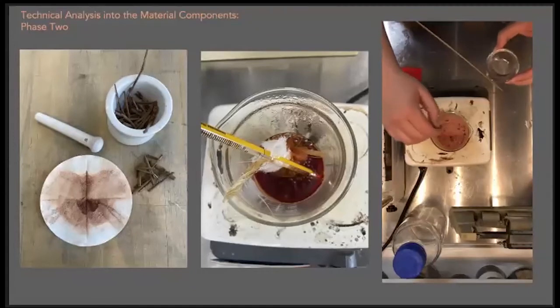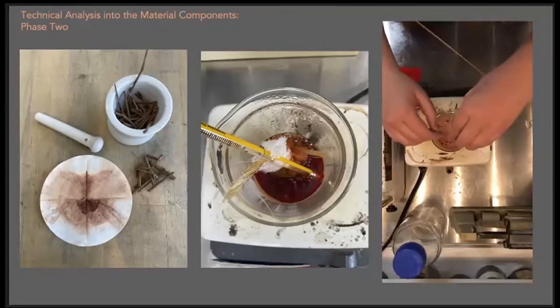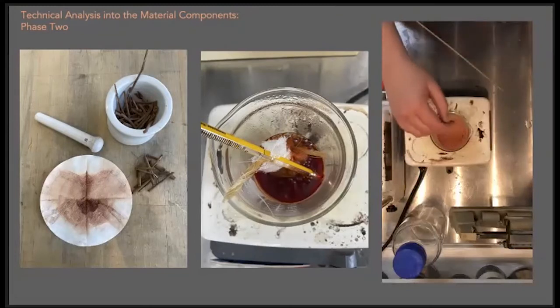In our case for cochineal and madder, we use potassium carbonate and potash alum. And the solution shown in the video on the right starts to effervesce or foam slightly as the reaction proceeds, and the pigment begins to precipitate to the bottom. It is then filtered and left to dry.